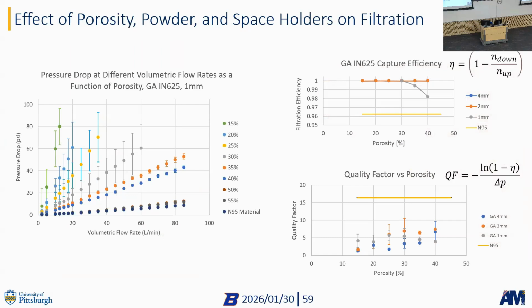Sam just sent me these results this week, it's Friday. As you can see here, for capture efficiency we are just going to 40%, also for the quality factor. But these are materials that don't have extra space holder in them, just sintered, right? Different densities. We are getting very close to N95 material for pressure drop. Pressure drop is how easy it is to breathe through these materials, right? So we're nearly getting there, while capture efficiency is pretty high. In these more dense materials, we're very, very high, better than N95 material.